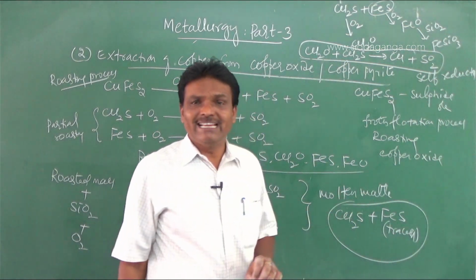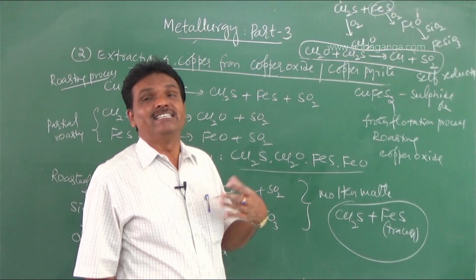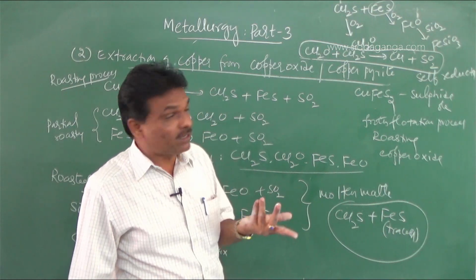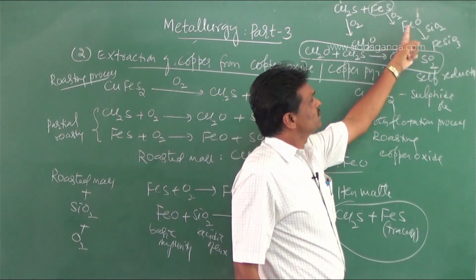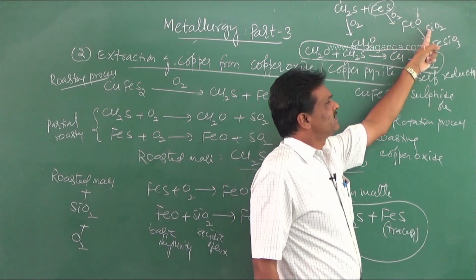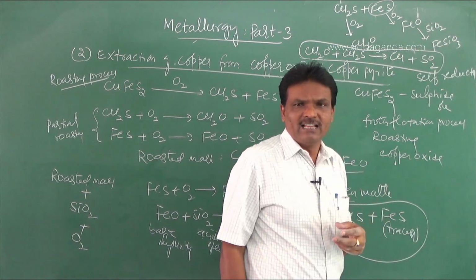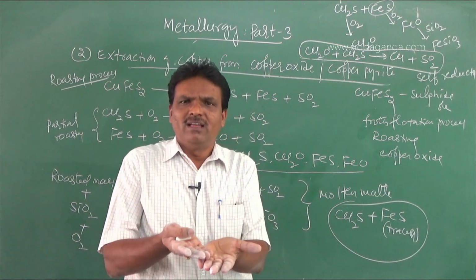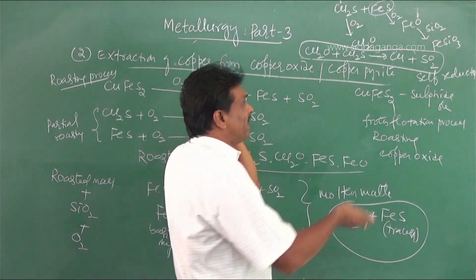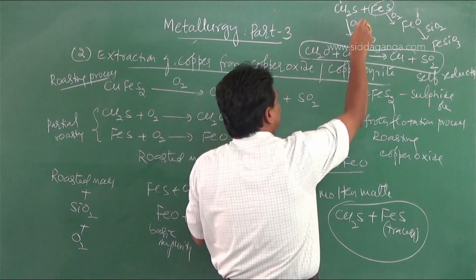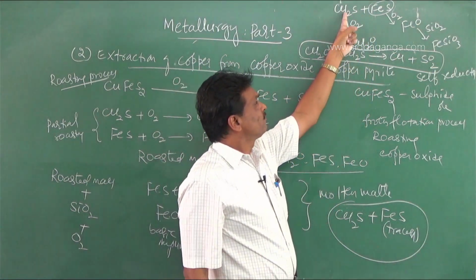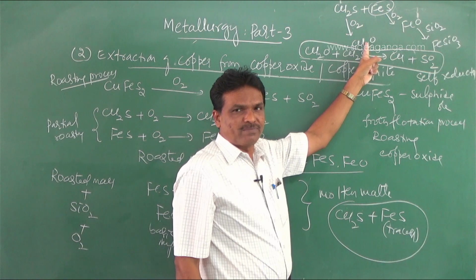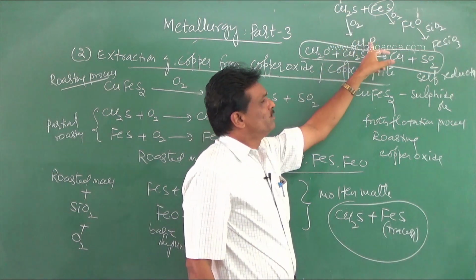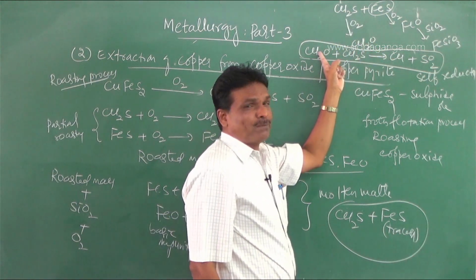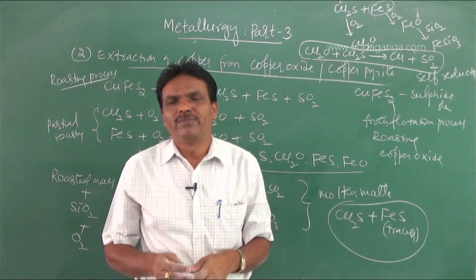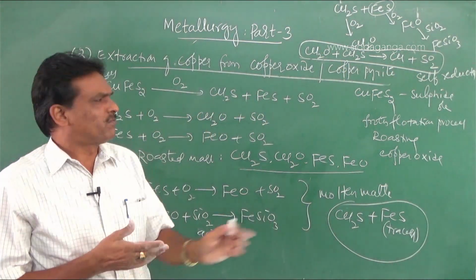This molten matte is mixed with a little silica and it is heated in the presence of oxygen in a Bessemer converter. The ferrous sulfide is oxidized to ferrous oxide. Ferrous oxide reacts with silica to form ferrosilicate slag. So it is formed at the surface of the molten mass. At the same time, part of cuprous sulfide is oxidized to cuprous oxide. And the remaining cuprous sulfide reduces the cuprous oxide obtained to copper metal. So this is the extraction of copper from copper pyrite.